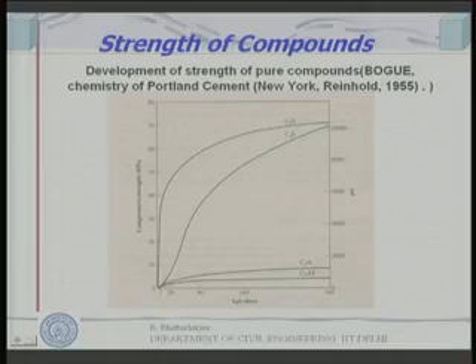Lime on the other hand is a non-sealing precipitate, it is sparingly soluble, it does not go into the solution so easily. So, it goes partially into solution, and it remains as a non-sealing precipitate in the pore structure of the cement paste, in the unoccupied space of the cement paste. So, CSH gel is the main strength giving compound in cement, and we know C3S produces high CSH in the beginning, therefore, it gives you the early strength.